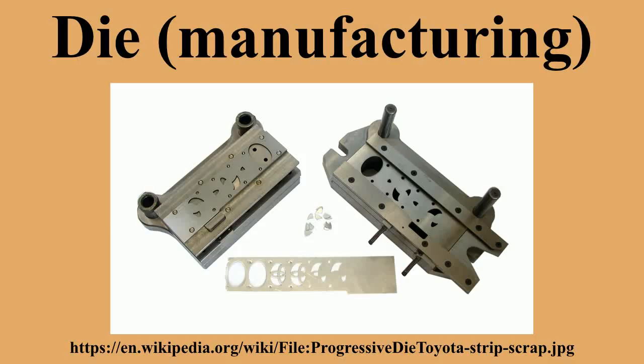If the lubricant is soap, the friction of the drawing of wire heats the soap to liquid form and coats the wire. The wire should never actually come in contact with the die. A thin coat of lubricant should prevent the metal-to-metal contact. For pulling a substantial rod down to a fine wire, a series of several dies is used to obtain progressive reduction of diameter in stages.